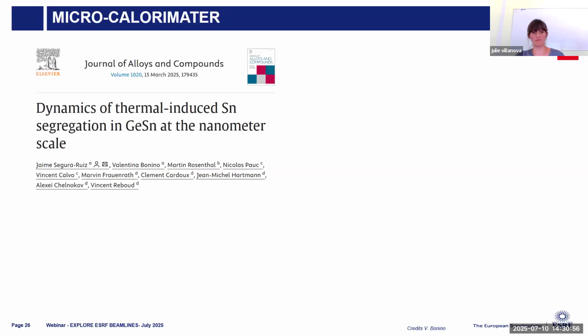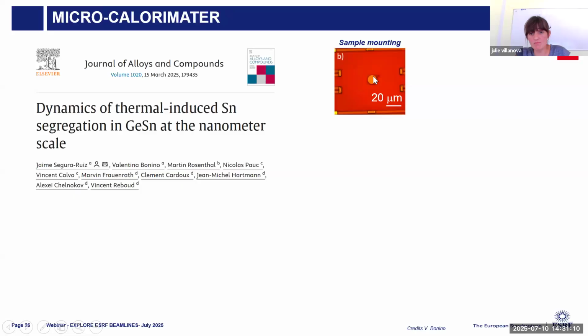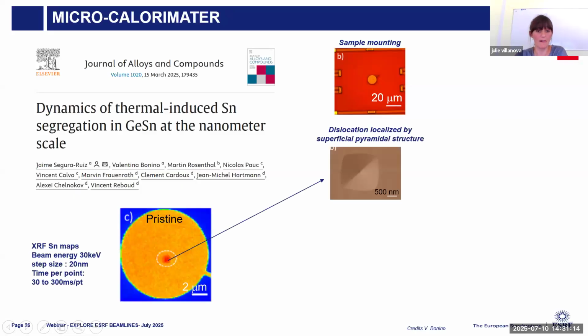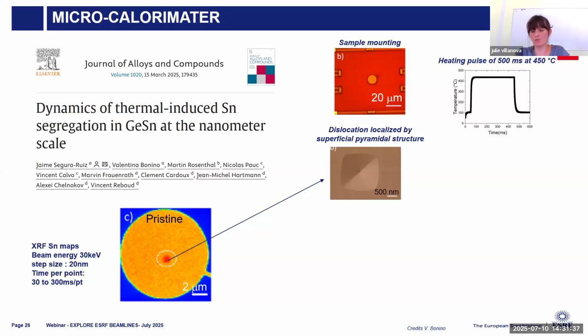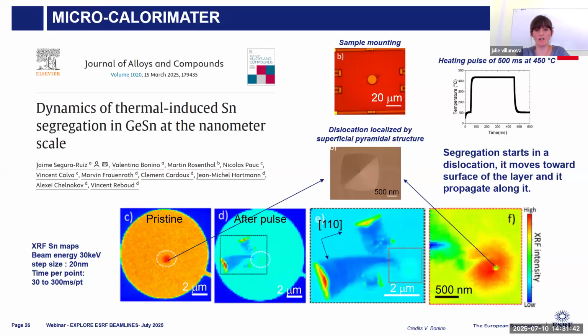So to illustrate the use of this device, here is a study about the tin segregation in a germanium-tin microdisc that you can see here on the top right. The microdisc has been mounted in the middle of the active area in the microcalorimeter. This is a 2D XRF mapping of the tin in the microdisc. And here where you have the red spot, it's in fact a nano-indentation that has been created in order to create some dislocation. And then the sample has been heated up in a pulse mode at 450 degrees. If we perform the XRF map after the heating, what has been seen is that indeed you have a segregation of the tin starting from the dislocation point, which is exactly the hypothesis of the scientists.